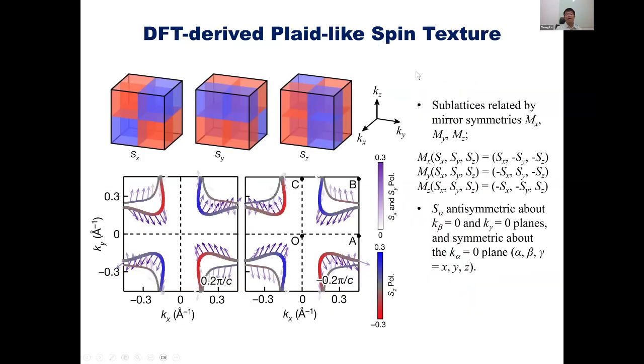So in theory, we have the spin texture derived from DFT theory. The arrow here corresponds to the in-plane component of the spin, and the color corresponds to the out-of-plane component of the spin. You can see that the in-plane component of the spin is antisymmetric with respect to these two lines. Here it is also antisymmetric with respect to these two lines.